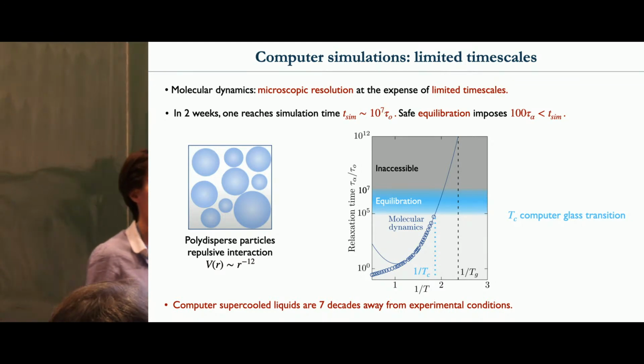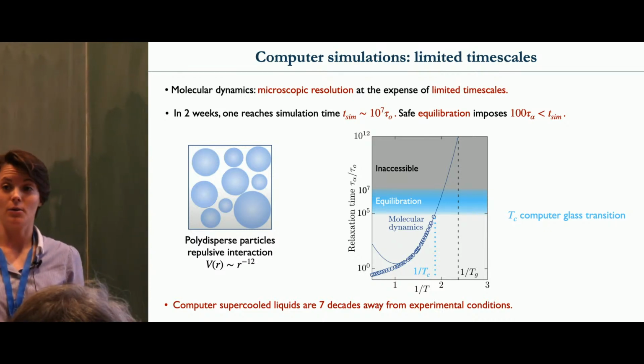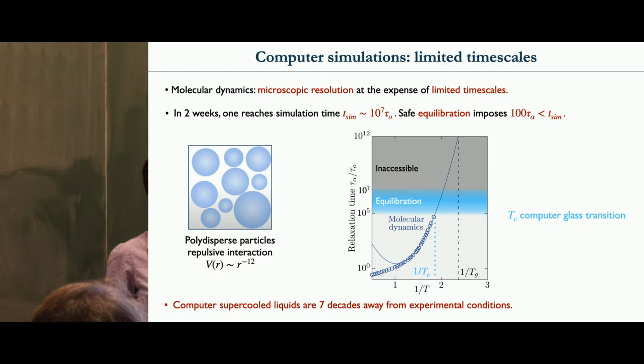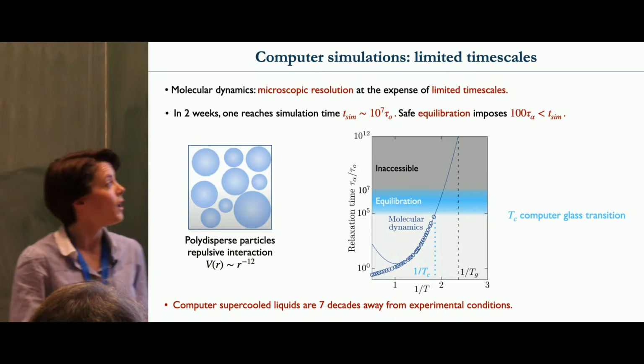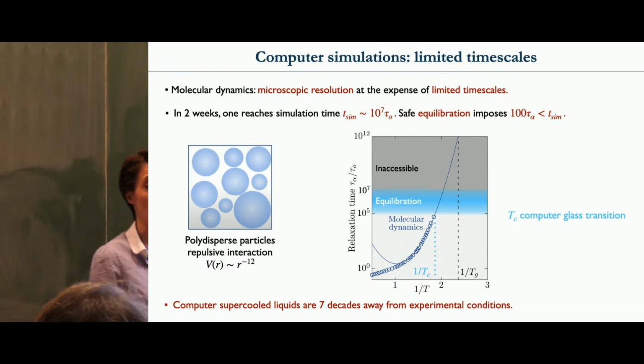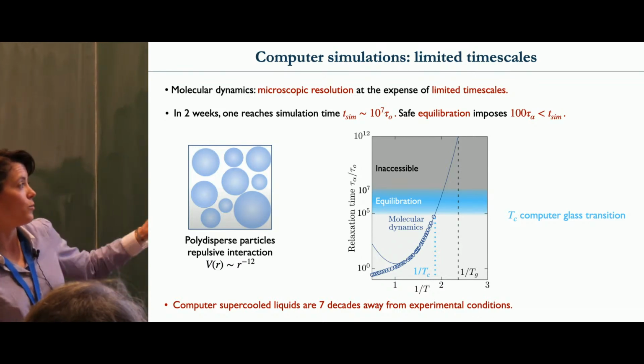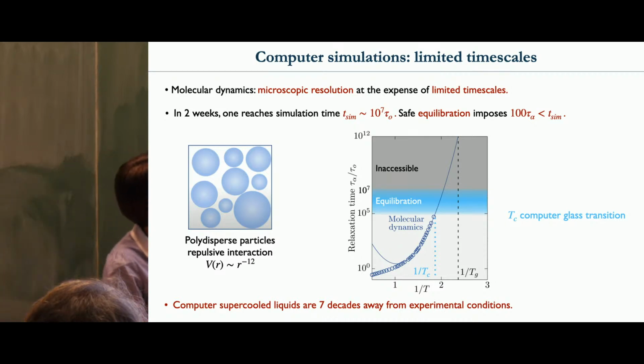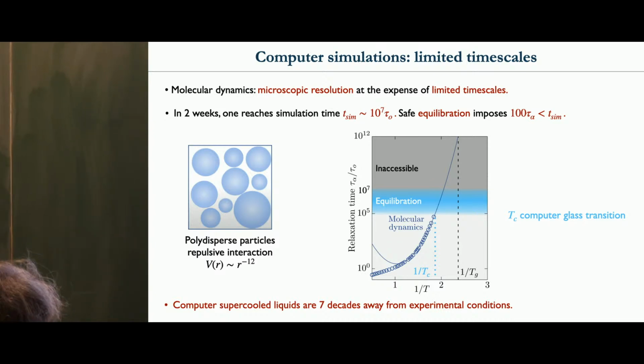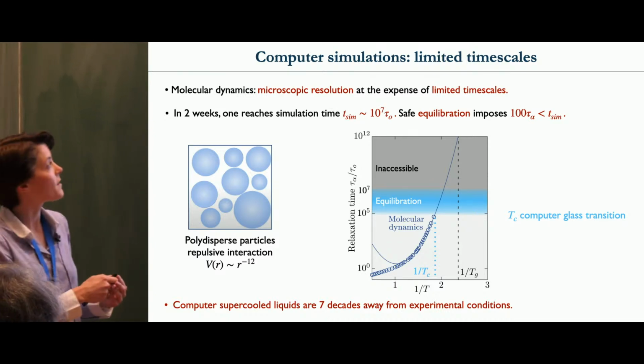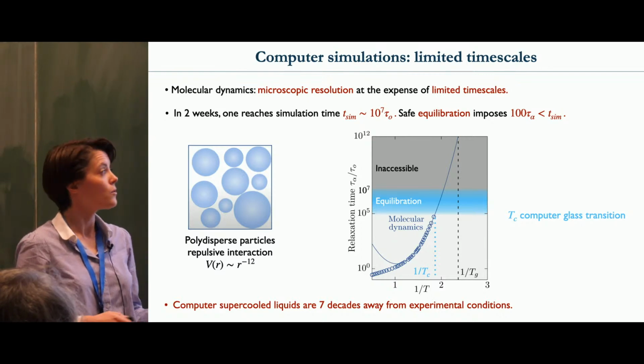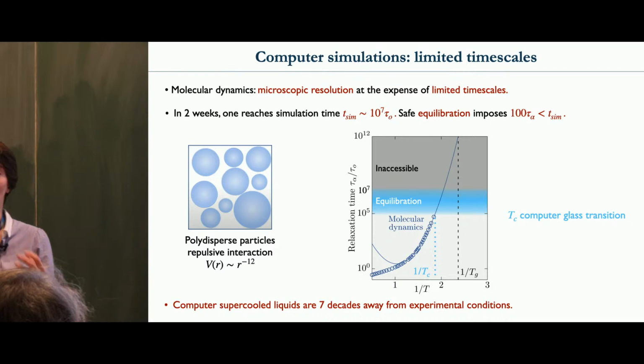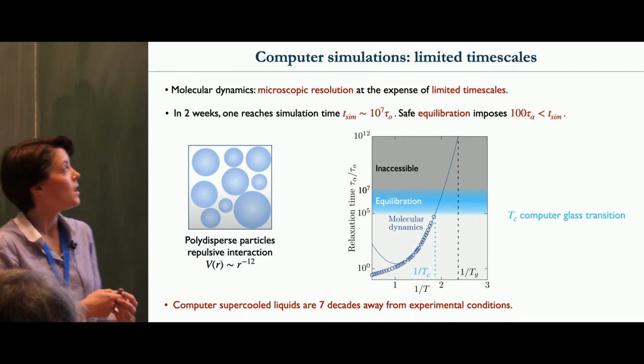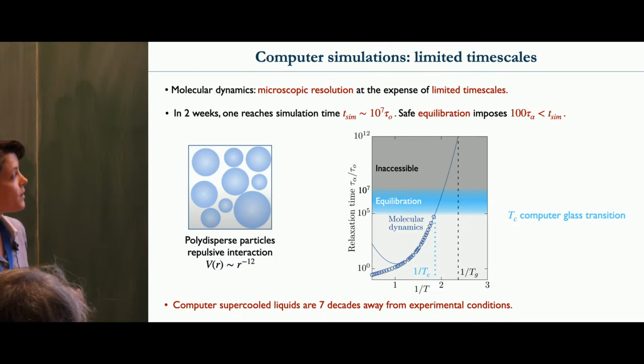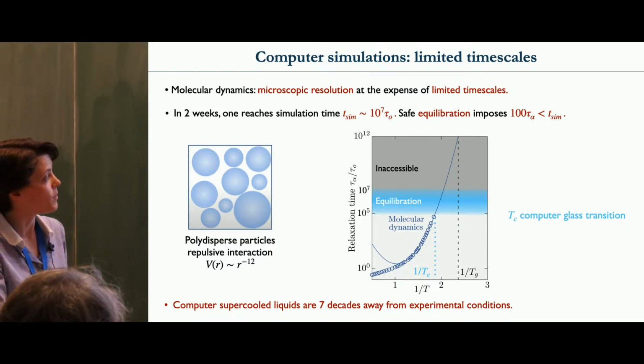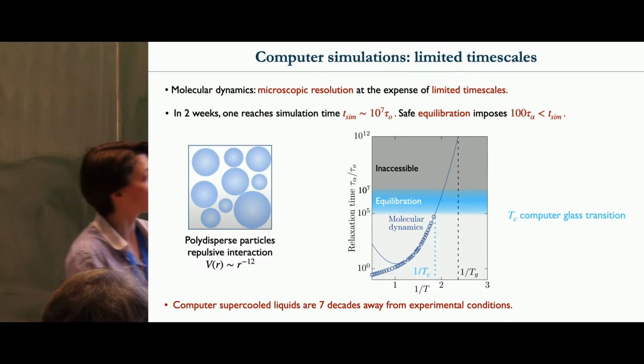The problem is that there is an expense to this. Computer simulations are much slower than nature and real experiments. So this has been a huge limitation for most studies up to now. So I want to go through some discussion about the timescales here. In a simulation in around 2 weeks, which is a reasonable timescale, you can simulate up to 10 to the 7 tau 0. So tau 0 here is the relaxation time at which you start to see this glassy slowdown. So this is the timescale that you have. So in this plot here, this corresponds to this limit here, so 10 to the 7 in these rescaled units.